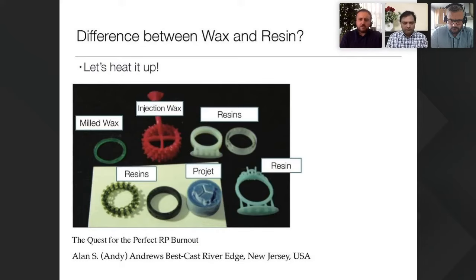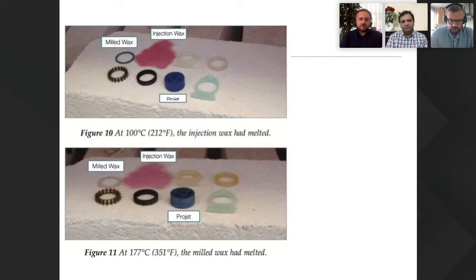So they took all those samples and fired them up, basically heated them. What happens is at 100 degrees on the top side, you can see that already the injection wax has melted, okay? It didn't disappear, it didn't fly off, but it has melted. But the whole resin parts are still there. The milled wax seems to be stronger as well, so it's still there.